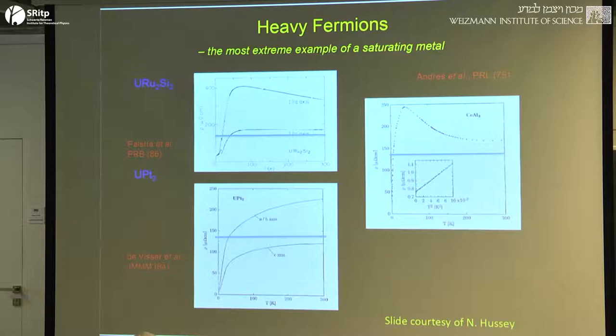Resistivity saturation of some sort or other is seen in a variety of different materials. This is from a review article by Nigel Hussey. This is uranium ruthenium 2 silicon 2. It's the resistance in two different crystallographic directions. Here again is my 135 microohm centimeters, not caring about what elements I'm looking at and so on. And I think you'll agree that at least this saturation value is sort of roughly determined by this quantum of resistance, actually to a remarkable extent. This a priori theory doesn't do so badly when everything else breaks down in many cases.